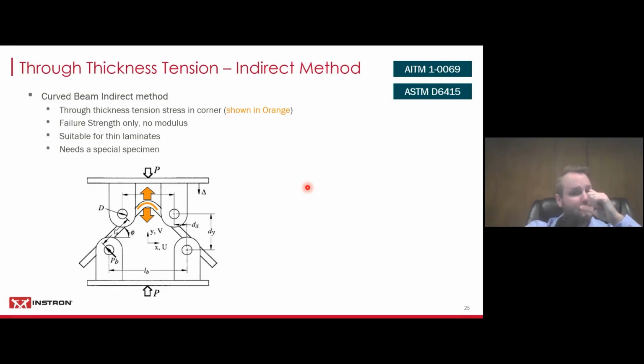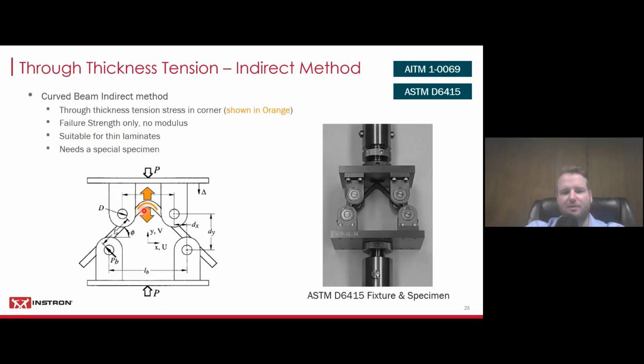Now moving on to through thickness tension with the indirect method. There's an Airbus standard that covers this, but there's also ASTM D6415, which I think is being revised right now in the committee. This is a curved beam indirect method. So you have a through thickness tension stress in the corner up here. It gives you failure strength, but you, again, cannot determine the modulus with this test method. It's suitable for thin laminates as well, though it needs a special specimen and fixture.